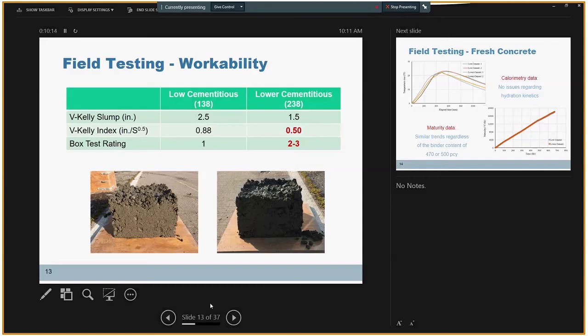So for the concrete with low cementitious material content, we had good workability indexes. The V-Kelly index was 0.88, and we had a box test rating of 1, which corresponds to less than 10% of voids at the surface of the sample after vibration. And for the V-Kelly index, we typically recommend a rate of 0.6 up to 1 inch per square root of second to have a good concrete that is responsive enough to vibration for slip-form paving.